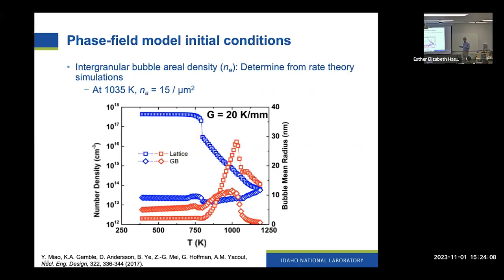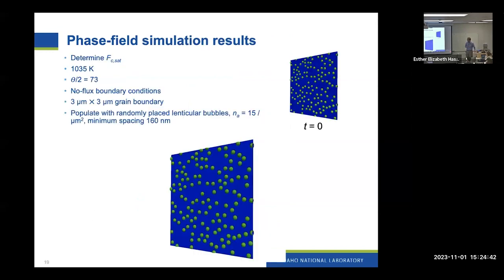One other parameter that we need to set up our simulations is the initial density of bubbles. Phase field in general does not say much about nucleation. So in this case, we started out with a bubble density that we took from rate theory simulations done by colleagues at Argonne National Lab. With their help, we were able to convert their rate theory models to an initial bubble number density along the grain boundaries. And that lets us set up our initial conditions.